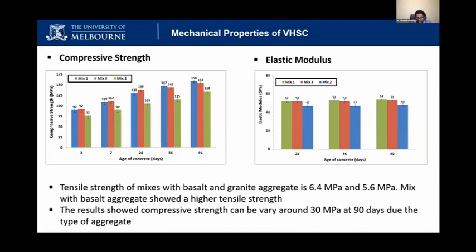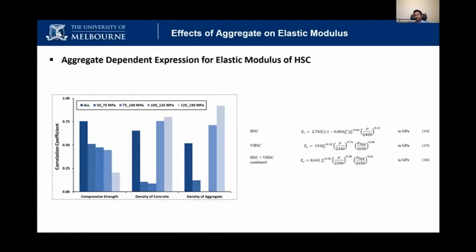We know that for normal strength concrete, the elastic modulus is around 20, 25, 30, somewhere around there. But for this high strength concrete, we can clearly see it's double the value of normal strength concrete. So this will reduce the axial shortening significantly. This is a critical thing in a tall building, reducing the axial shortening, the deformation. I saw the drawing of this 1 kilometer tower in, I think, Saudi Arabia. If you look at the drawing, they have specified two things. The first thing is the strength. The other thing is the elastic modulus, because of this axial shortening and deformation. So when we specify high strength concrete, we have to achieve two things, the strength and the elastic modulus. That's why it's really important to use the right aggregate, because if you use the right aggregate, we can get the right strength and also the elastic modulus.